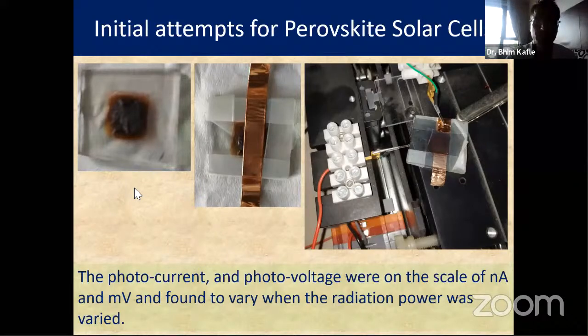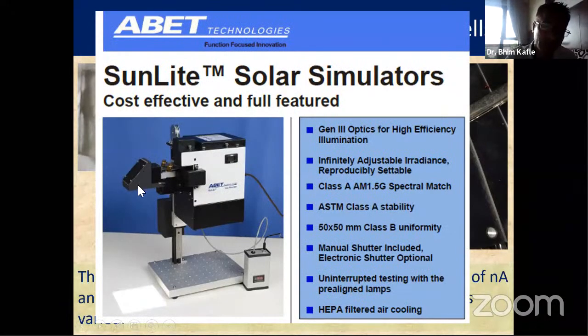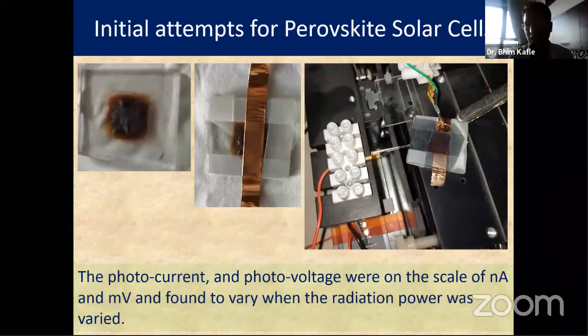For example, this is a sun simulator that we have, it produces visible light, and our sample was exposed here. You can see the range of this light. Our sample was here, and once you expose it, you get photocurrent and photovoltage. And we varied the intensity, and after varying the intensity, we could see variation in the current. It means that it is working as a solar cell, but there is a severe problem. Maybe a large amount of electrons were lost, maybe at the interface, or by recombination because of large defects in the RGO, or in the TiO2 itself. We mostly expect the loss is in the interface between RGO and the copper, because mostly people do this, and it is not a good contact.